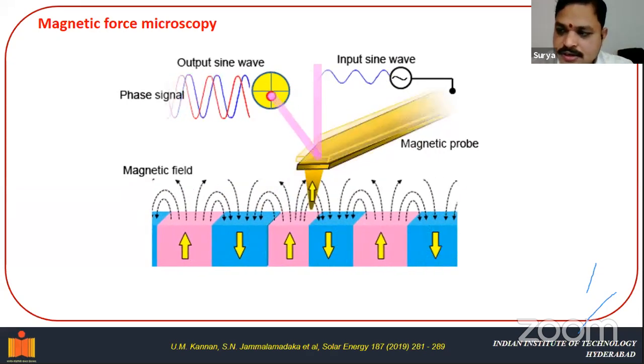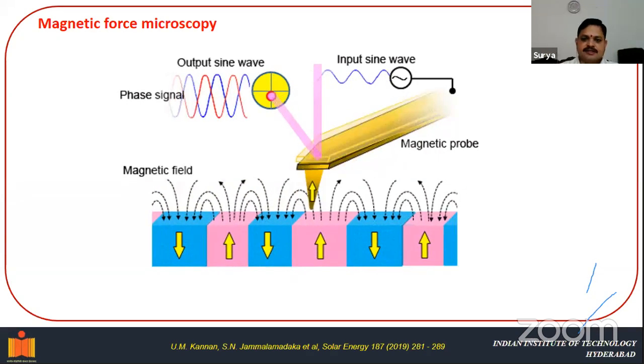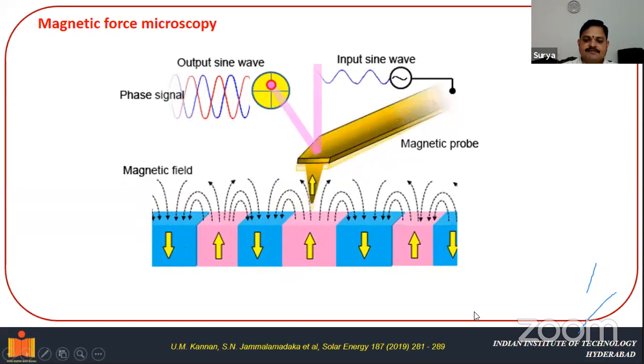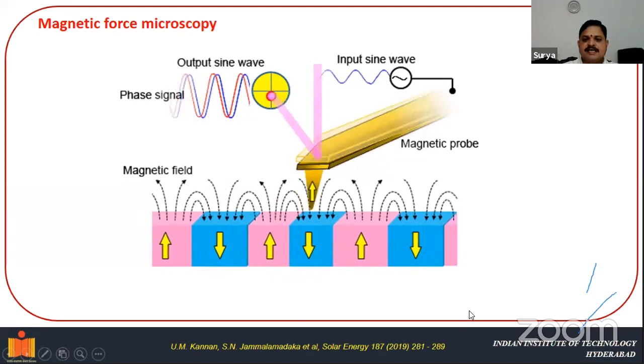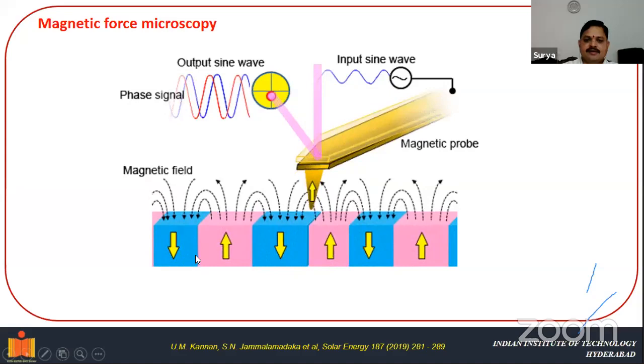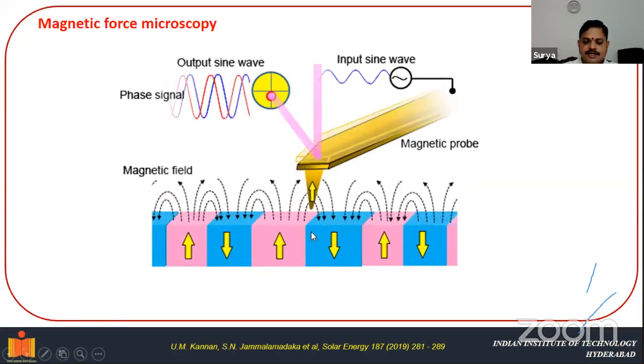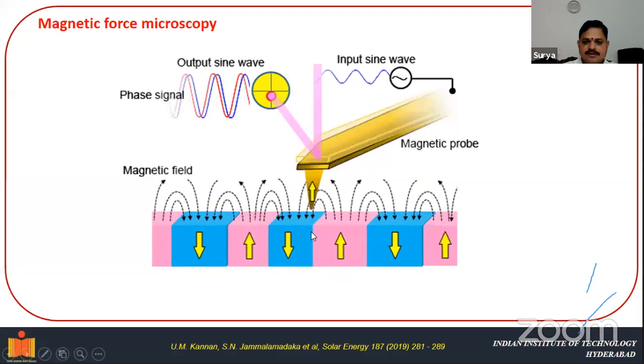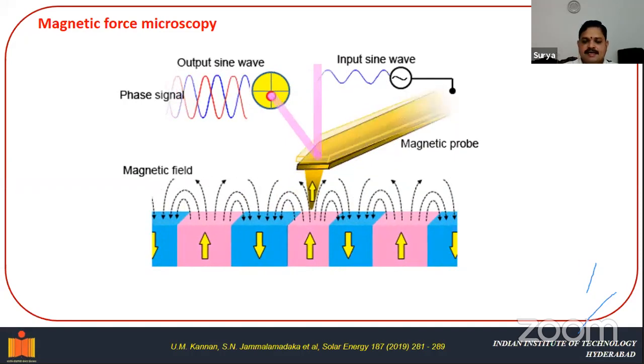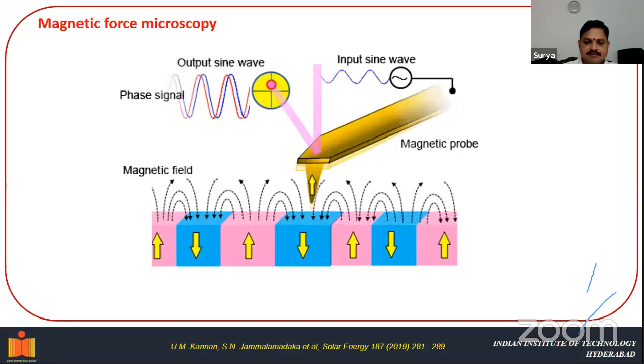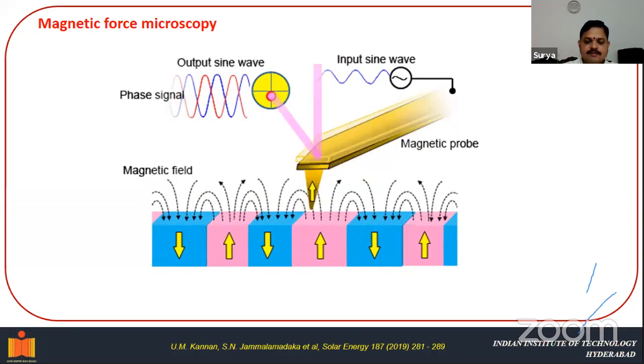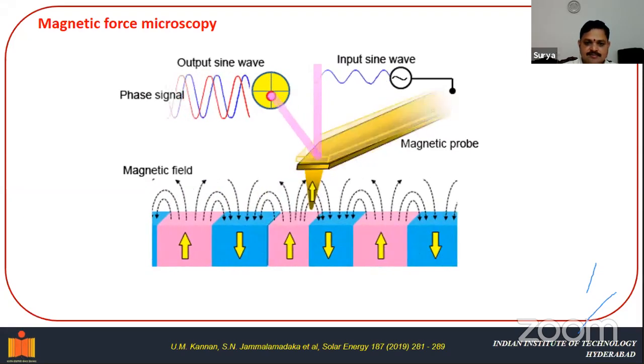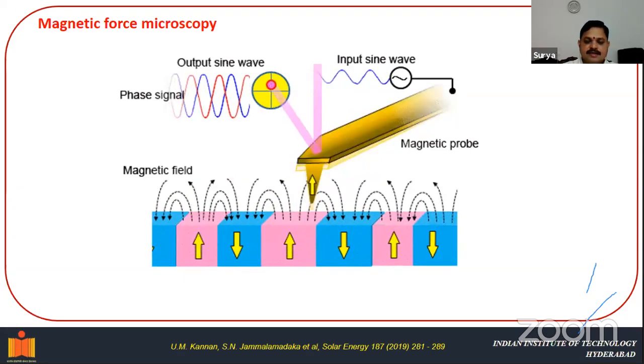This will give the magnetic phase, what kind of phase exists. From the phase analysis, you can actually say whether the magnetic moment is oriented in the up direction or in the down direction, based upon the color contrast. Suppose the magnetic moment is up, you can observe the bright contrast. If it is down, you can observe the dull contrast.